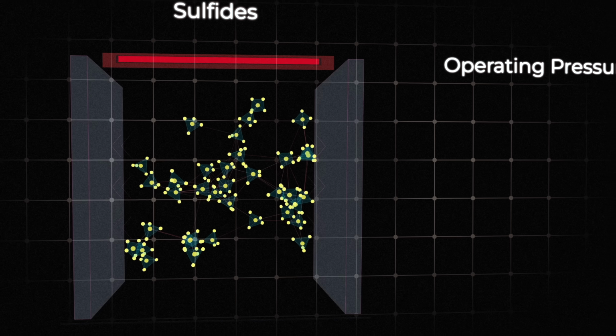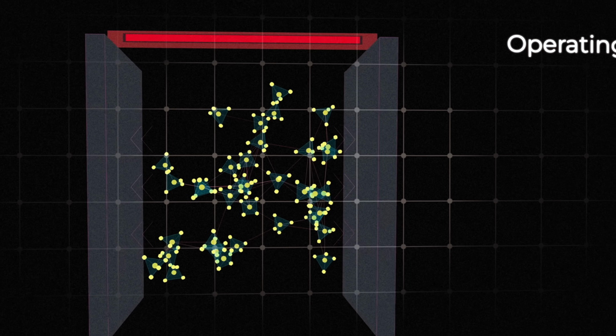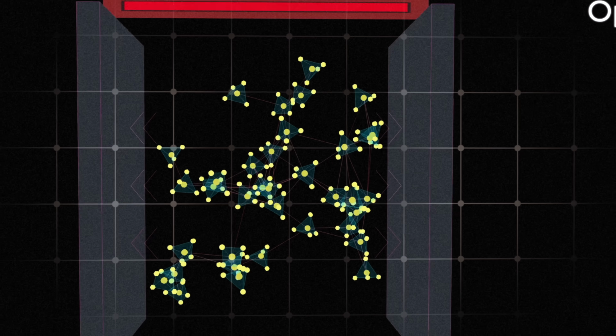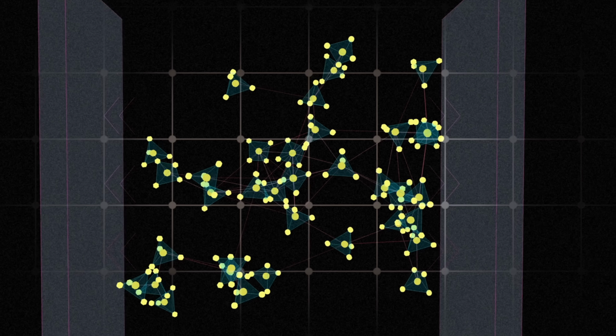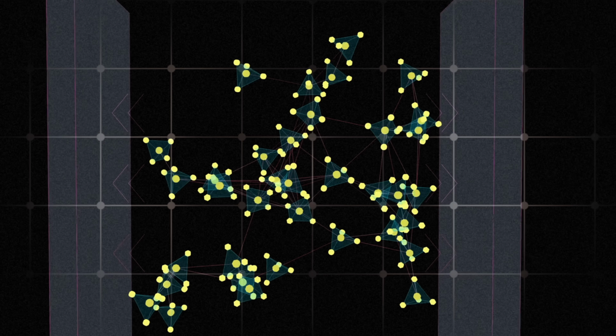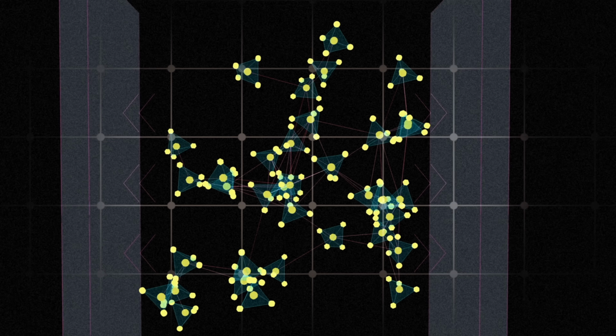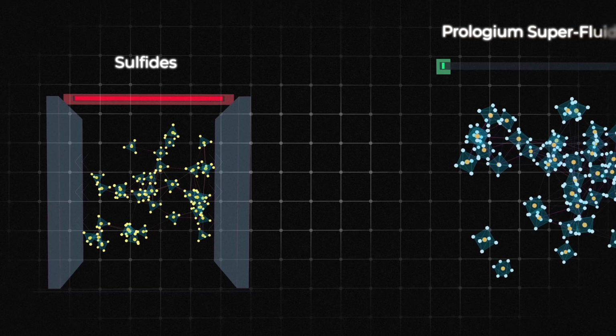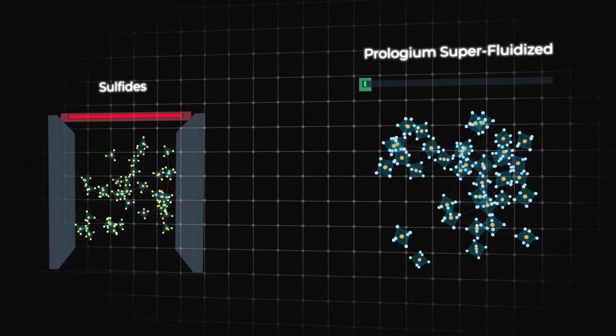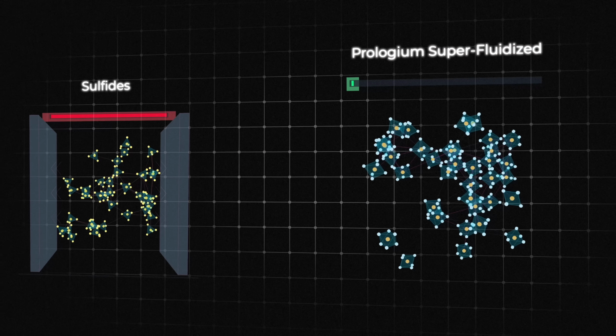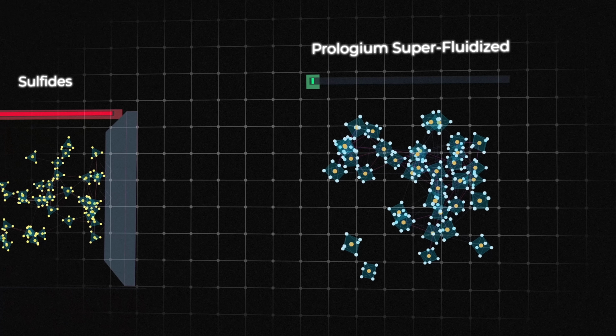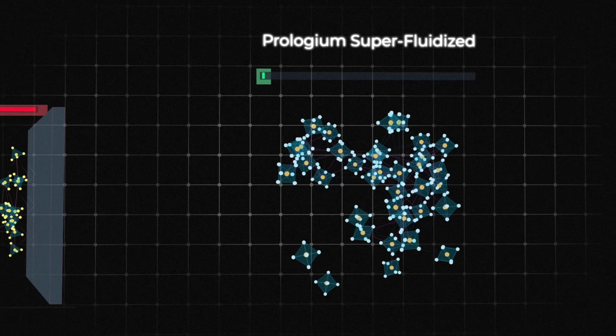Why? Because sulfide particles expand and shrink during every charge and discharge cycle. They lose contact with each other, and the only way to keep them touching is to mechanically compress the cell from the outside forever for the rest of the life of the battery. Now this means higher mass, higher cost, and you can't even use them on phones or drones because the pressure system alone would weigh more than the battery itself. ProLogium superfluidized electrolyte handles this completely differently. The gel texture network self-maintains contact through every charge cycle without permanent external compression.